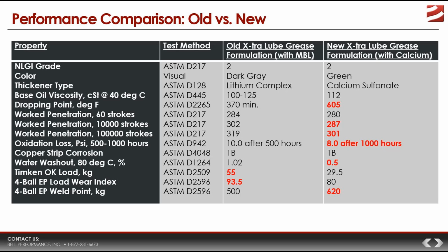But sometimes they might take that same fatty acid, and the same metal hydroxide, but this time they might throw in an additional acid into the mix, what they might call a short-chain organic complexing acid. Long and short of it is that when you do that, you get a calcium complex soap. And the reason why we're bringing this up is because calcium complex soaps can be used to make greases that have much better or higher temperature properties.